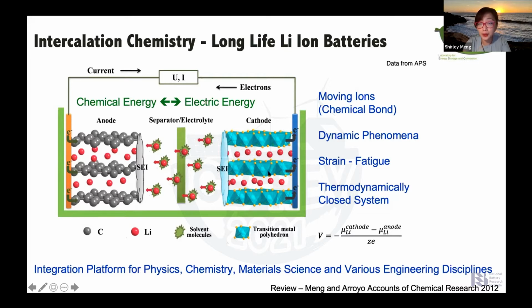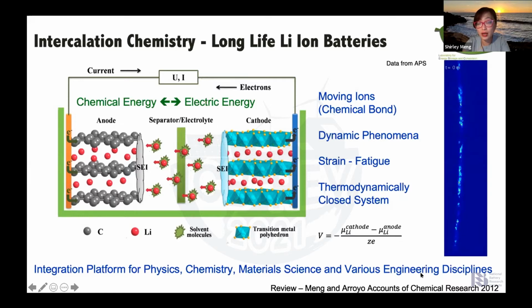Lithium ion is actually a big ion. It occupies large space. If I take an X-ray photograph, like X-ray diffraction of the battery, you will see how the X-ray peak moves when you charge and discharge the battery. You can see the peak moves, and sometimes one peak becomes two peaks. That's a phase transition. And when you discharge the battery back, the process has to be completely reversible. One doesn't realize this, because your cell phone battery is typically enclosed in a hard casing, so you don't really visualize the volume change, but the X-ray tells you what your eyes cannot see. In fact, every time you discharge your battery, the volume change for these intercalation materials will happen.